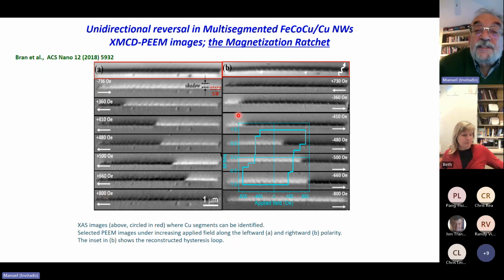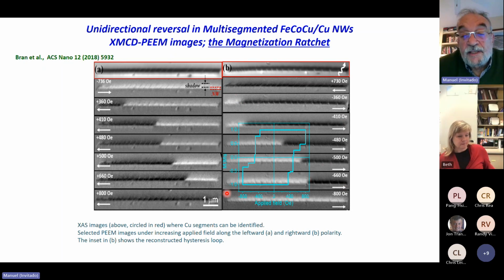Then if we start with the opposite situation, black saturation under a positive field, and we apply a negative field of increasing amplitude, we observe again a reversal of magnetization in different steps as we increase the field until getting the final saturation. But interestingly, the reversal occurs also starting from the left end of the nanowire, where we have the shortest magnetic segments. And it is possible to reconstruct the hysteresis loop of this individual nanowire.